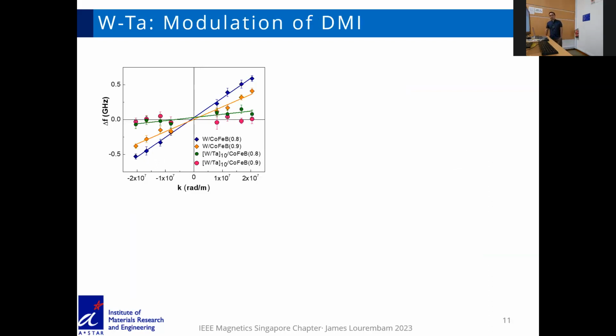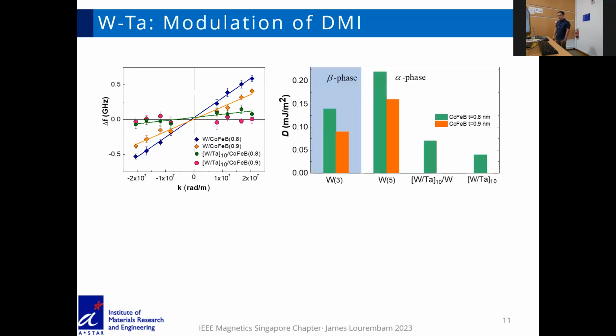As expected, because of the linear relation in the previous slide, we do get a linear relation of delta F versus momentum. And from this slope, we can get the DMI in the system. The DMI in the beta phase was found to be slightly lower than the alpha phase. And because DMI is an interfacial property, as you thin down the CoFeB, the DMI will increase, since it's coming from the interface between tungsten and CoFeB.